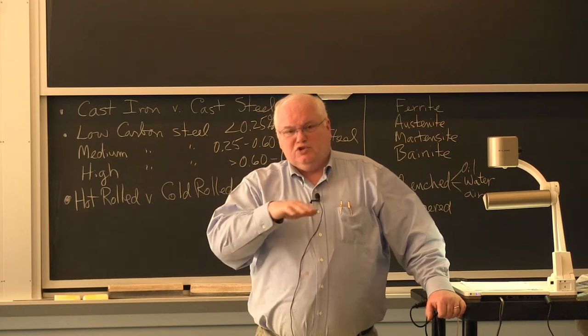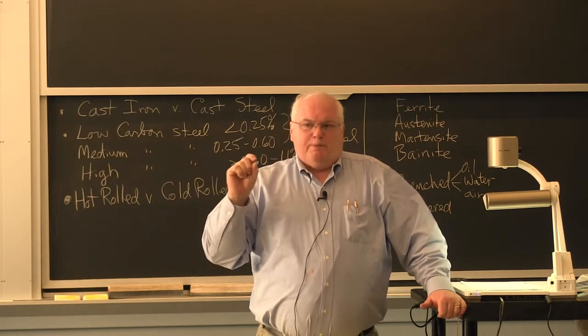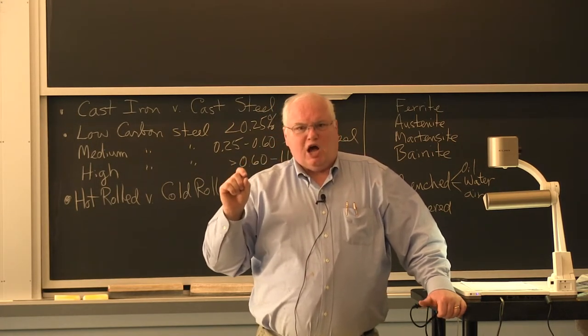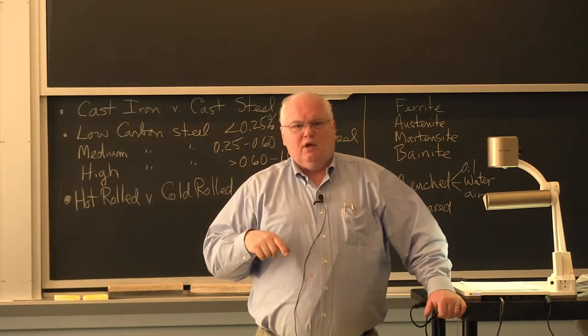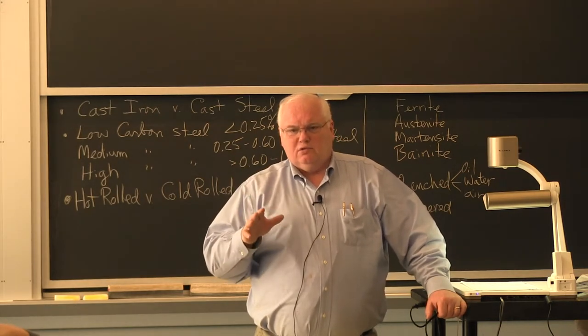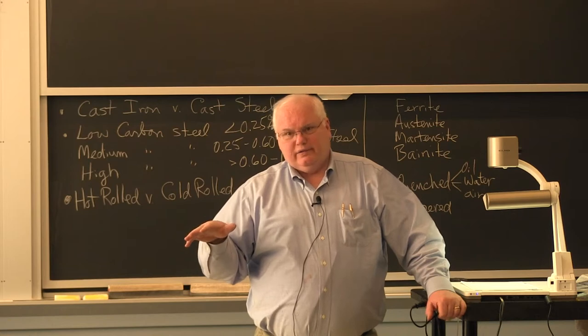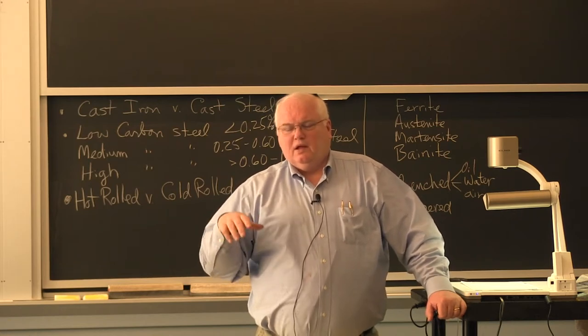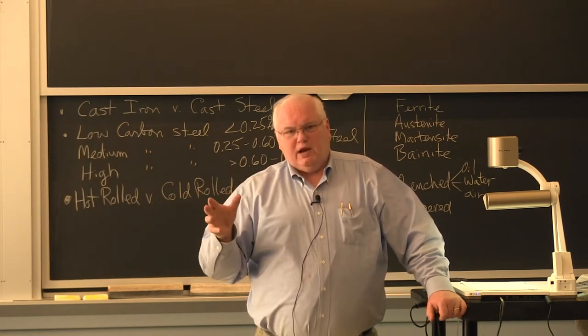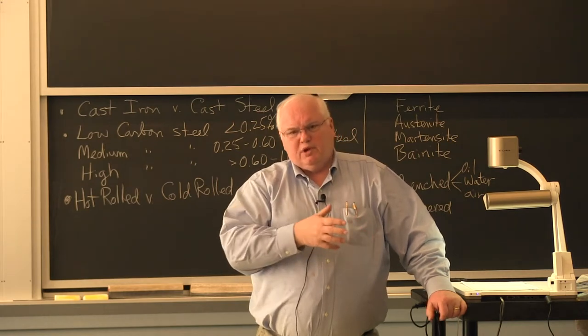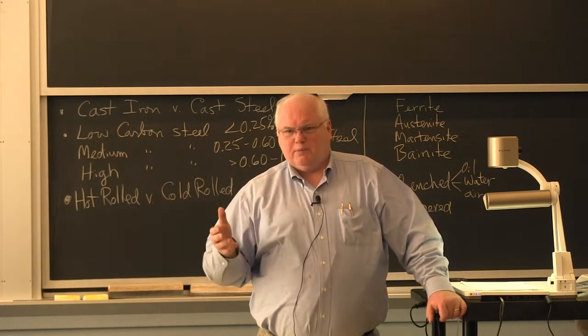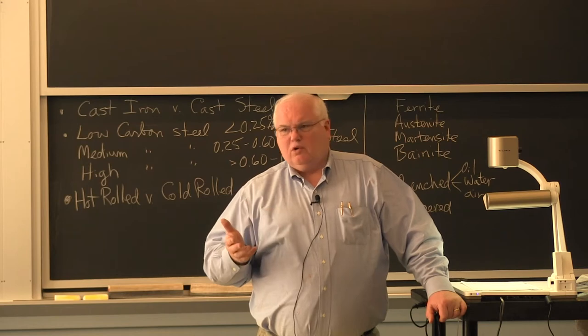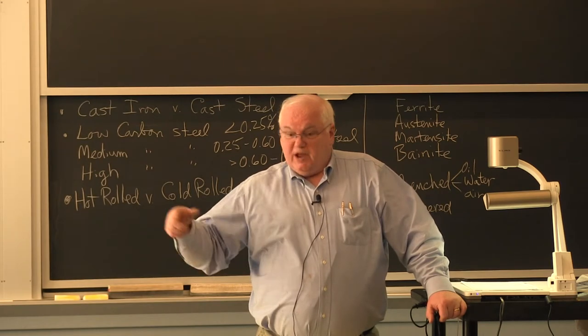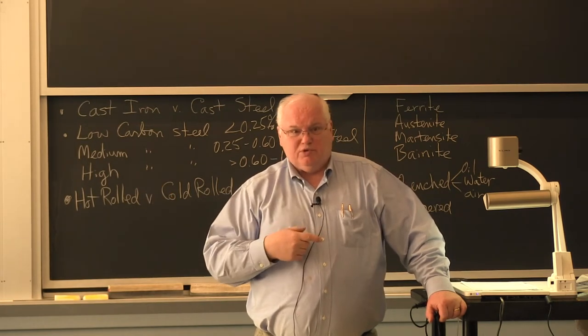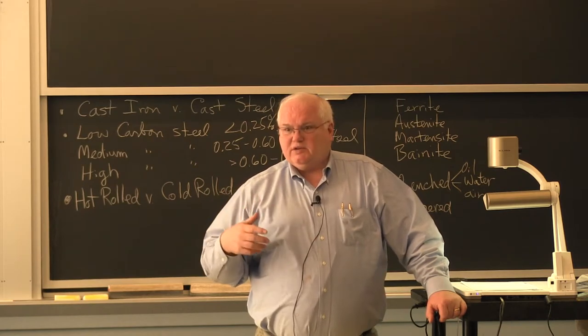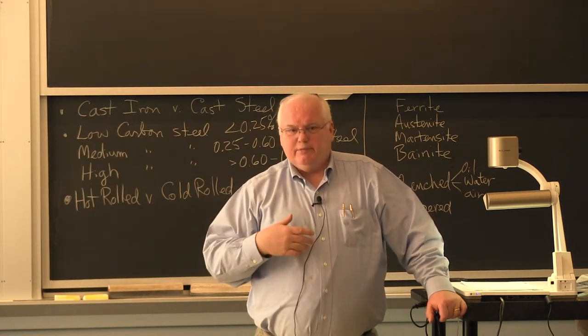But basically you can break it down to about a quarter of an inch thick, and that's hot rolled strip, and you put it in a coil while it's still hot and let it cool, and you call it hot rolled band, okay, B-A-N-D. You take the hot rolled band and you take it over to another mill, which might be a $1.5 billion proposition today, which is called a cold rolling mill. And now you're basically going to put it through at room temperature through these big massive rolls, and it'll be going through there at 60 miles an hour.